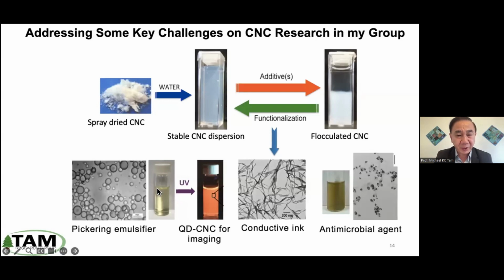We have produced quantum dots on a CNC that are very stable, and we shine UV light, it fluoresces, so that's good for imaging. And we can coat this particle with conductive polymers to make conductive ink for different electronic applications, and we can nucleate various metallic or inorganic nanoparticles on the surface and produce systems that have antimicrobial properties.